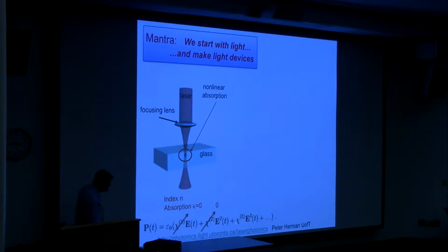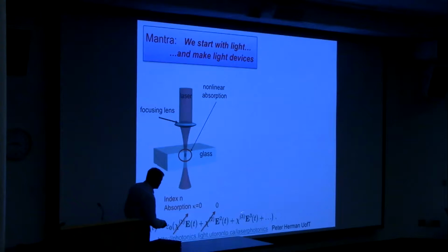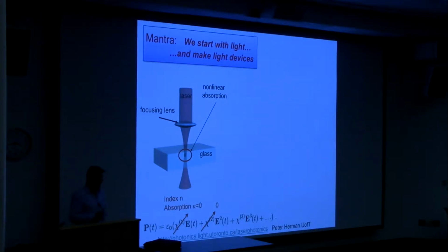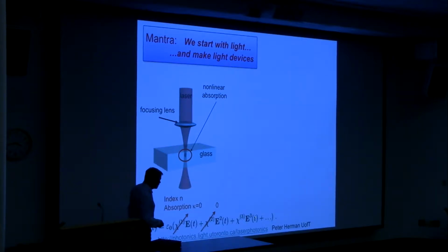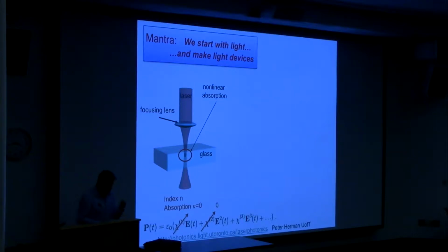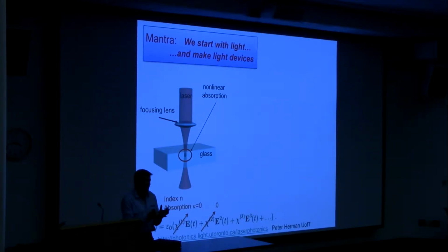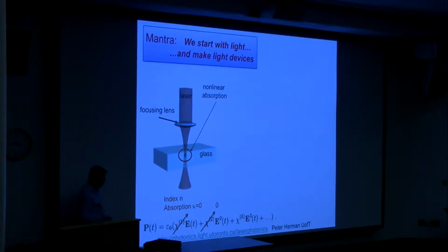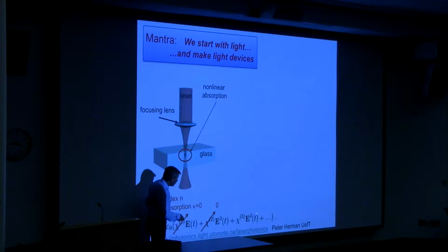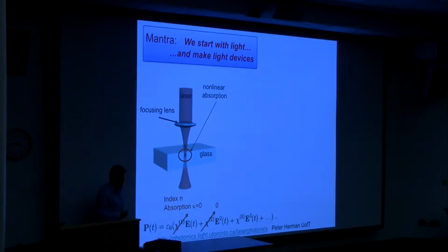So what you need to do is you need to turn on the so-called chi 3 process, third order. These processes are enhanced by the third power of electric field. So if you double intensity, this could be 8 times more strongly interacting. So how do you get strong electric fields? Well, focusing obviously is one approach, but the other approach is that there's a certain amount of energy you need just from thermodynamics to reach a threshold of modification. The idea is to take that energy and apply it in shorter and shorter pulse durations. And so when you get down to, say, picosecond or in the femtosecond domain, that amount of energy is more than enough to turn on and drive both real and imaginary parts in chi 3. So out of this then come refractive index effects with these short pulse lasers. Refractive index might be a Kerr lens nonlinearity, which leads to self-focusing, forming filaments and other effects.